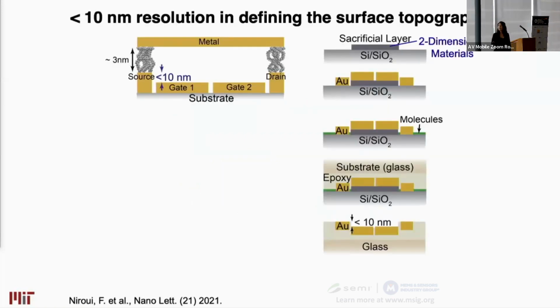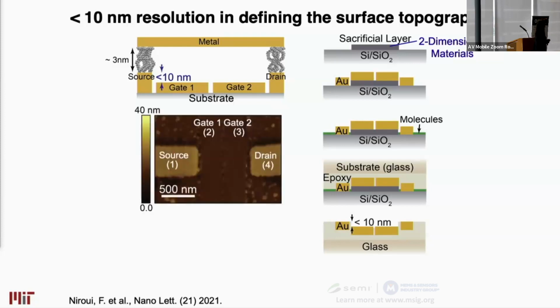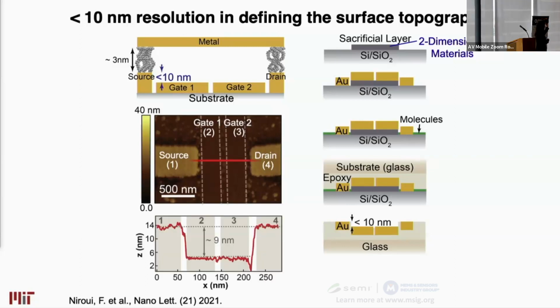So we go ahead and come up with ways of being able to fabricate such structures. In this particular example, I won't go through detail, but we've come up with a way of being able to fabricate the surface topography with sub-10 nanometer surface variation between the source drain and the gate electrodes. So in this case, here I'm showing you an AFM, atomic force microscope, topography image of an example electrodes. You can see that the middle two gate electrodes are recessed about 9 nanometer relative to the source and the drain.